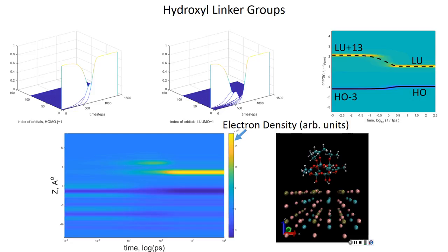And 10 to the 0 will be 1 picosecond. So it's sometime between 100 femtoseconds and 1 picosecond. Right. Technically, you're reaching your charge transfer in the 100 femtosecond, sub-picosecond range. It's extremely quick. Is it good or bad? That's good. You'd expect it to be very beneficial.